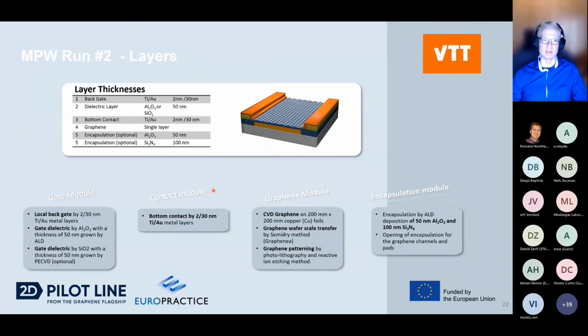The layers in this process include the backgate, which in our process is titanium gold with a thin titanium adhesion layer and then a 30 nanometer gold layer. For the dielectric layer, there's an option to have either aluminum oxide or silicon dioxide. Thickness is 50 nanometer, and the bottom contact layer is similar to the backgate layer. There will be titanium gold there as well. The graphene is a single layer graphene, and in the encapsulation part we have the aluminum oxide and silicon nitride combination there. So the same here. So the details for the modules.